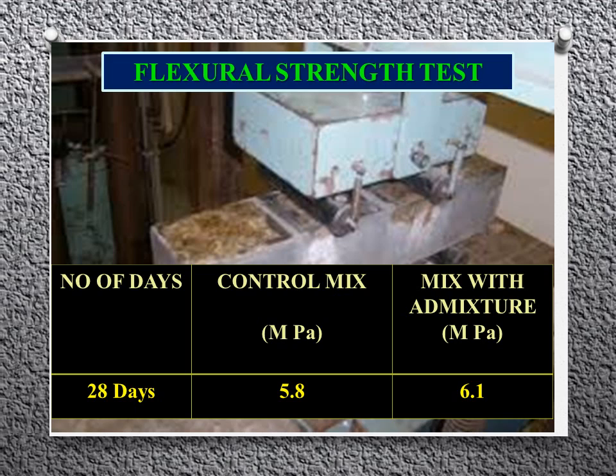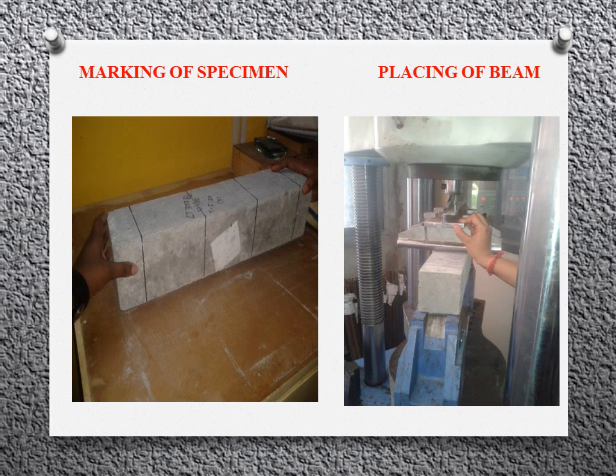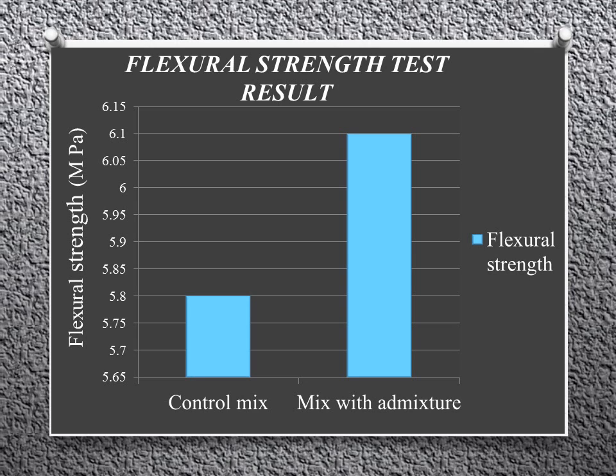Flexural strength test, which was carried out to find out the tensile strength at the age of 28th day for both the control mix and mix with admixture. Thus, the mix with admixture gives a higher value compared to the control mix. The pictures taken during the experimentation. The flexural strength test results are shown. Thus, the flexural strength value for the mix with admixture is higher compared to the control mix.